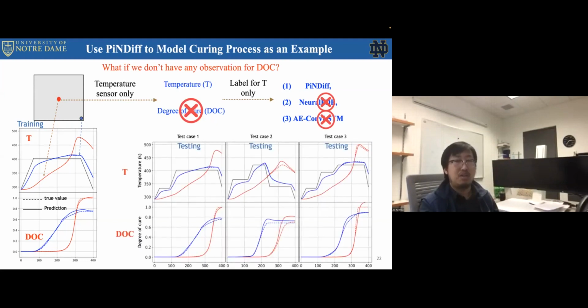And like I showed you before, I can just change the temperature profile and arbitrarily generate the testing temperature, like open autoclave temperature profiles. So basically the model can be generalizable to those scenarios. You can see the degree of cure and temperature time sequence profile looks different once you change the autoclave temperature profiles. There is some discrepancy, but remember, these are completely testing scenarios. So we are very happy about this result, especially considering that we only include the temperature as the training labels. So we can recover the degree of cure as well.